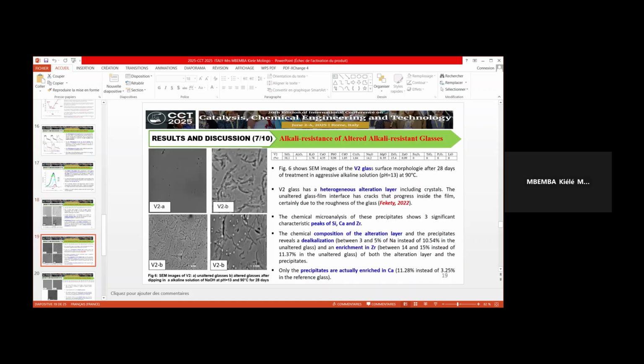Concerning the alteration of V2 glass, we can see a heterogeneous alteration layer, including crystals. These crystals are composed of silicon, zirconium, and calcium. We also note dealkalization, between 3 and 5% of sodium instead of 10% in the reference glass, and an enrichment in zirconium between 14 and 15% instead of 11% in the reference glass. And the precipitates are enriched in calcium.